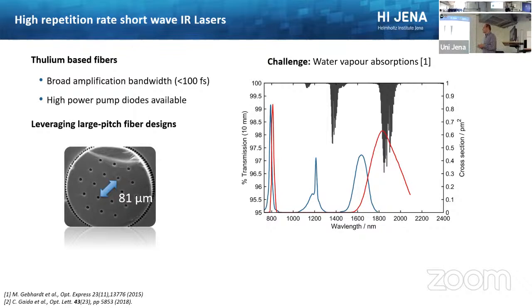Okay. But you're right, this is a bit more than you would normally, but not much more than you can do in a CPA regime, where I've said you can do multiple 100 microjoules depending on your stretching factor, maybe to a millijoule. So it's a bit more, but also a bit longer pulse duration because these were directly nanosecond pulses. But you achieve typically 1 millijoule per core.